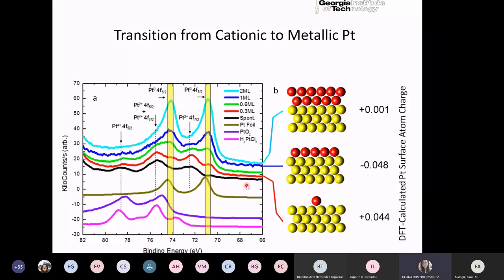Okay. All right, so let me again skip a slide and get to the result of that earlier study. The result of the earlier study is expressed in this cartoon, where we see that when you are less than one monolayer thick, then you have cationic platinum. That is platinum that is chemically bonded still to the nonmetals in kind of an ionic bond, and you have these platinum molecules stuck to the surface, and they're not very active for the catalysis. And then when you get to one monolayer, you still have a bunch of these molecules still present, and it's only after you get past two monolayers that you have a fully evidenced